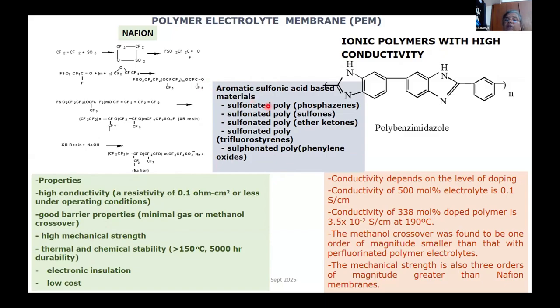A lot of studies have gone into many other aromatic polymers, and they have sulfonated these polymers and used them as polymer electrolyte membranes. However, their performance is not very good, and also their stability, because like I said, it is an oxidizing and reducing environment. So they are not very good in these kinds of atmospheres. As a result, they are not much commercially known.